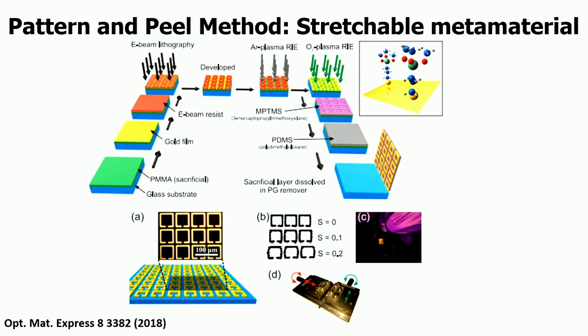So basically we have the glass substrate, we do the electron beam lithography, make these patterns, then we put MPTMS on top, then pour PDMS on top of it, and then just peel off. So the pattern gets transferred to the PDMS, and then we did these studies on such a structure.